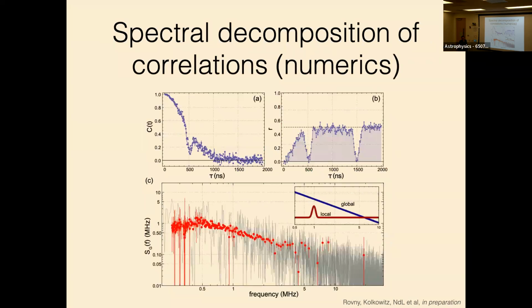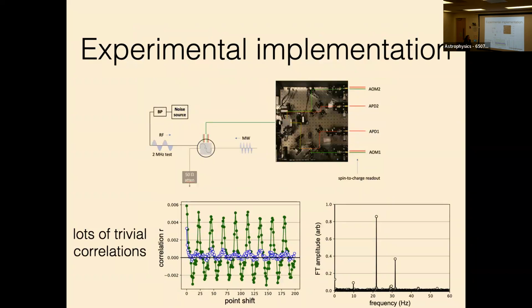Okay, so these are now some numerics. If you have an NV center that has this coherence decay, and you ask, if I have two NV centers that have this coherence decay, what do the correlations look like? Then, by quantum projection noise, you're stuck at a Pearson correlation of a half. And then, intriguingly, you see these dips wherever their local noise takes over. So it's a funny way of actually measuring these carbon-13 nuclei, where you see the correlations disappear. And then you can do things like spectral decomposition, where you can also look at the spectrum of these correlations. Okay, so that's as far as we got until January or February, and then we went to actually build this experiment.